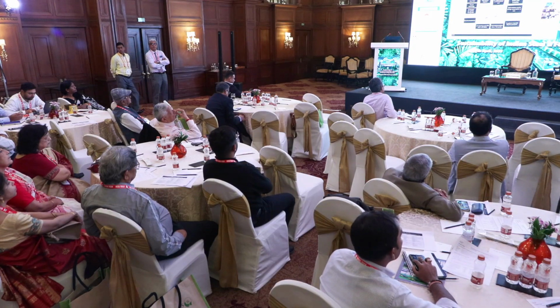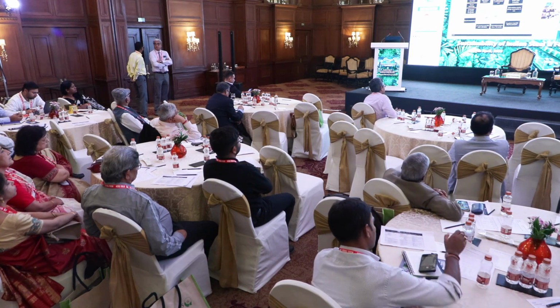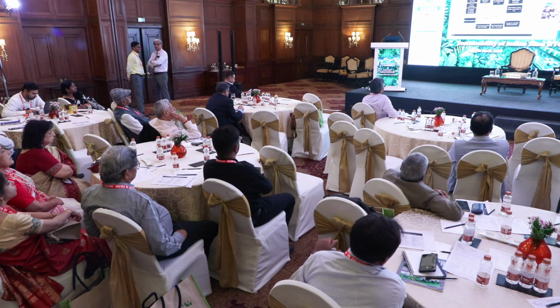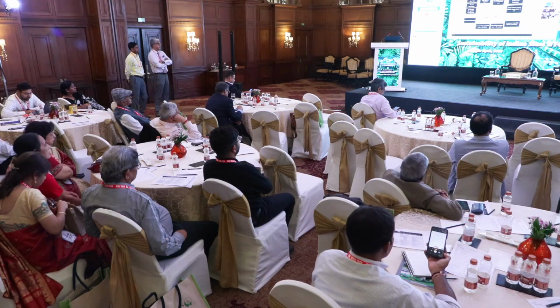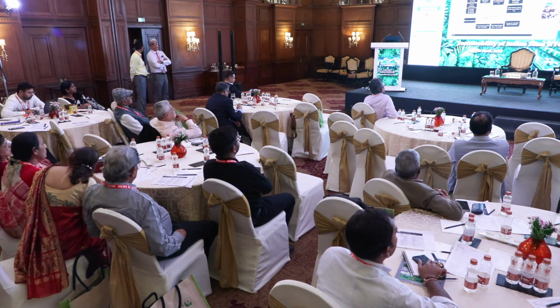And then you still have 20 megawatts of extra energy, with which you can heat up ladles, or create electricity, or other things. The agglomeration plant here, making the pellets, has a pelletizing cost of less than $20 per ton. And it greatly boosts the furnace productivity together with the preheating kilns, which means we can get 3,000 kilowatt hours per ton of ferrochrome energy consumption or less. Of course, this depends on the chromium content. With 50% ferrochrome it's of course lower than with higher chromium content. But anyway, it is based on high plant availability, high production, fewer and bigger furnaces, continuous operation, and is highly profitable.